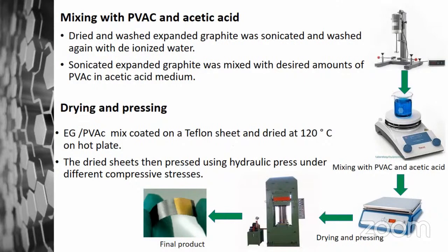To mix PVAC and acetic acid to generate the composite material, we must mix the graphite with a flexible material, which in this study is PVAC, polyvinyl acetate. Polyvinyl acetate cannot dissolve in water, but it can be dissolved in acetic acid. We wash the graphite and then mix it with PVAC and acetic acid. After that comes the drying process.